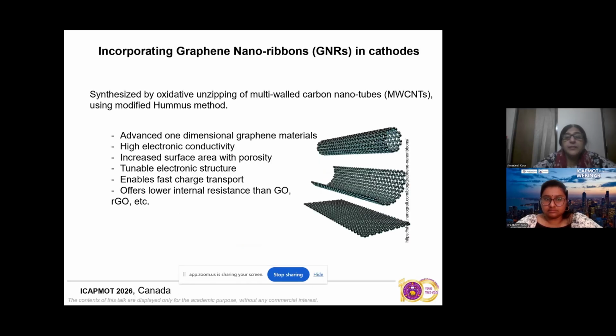So what we have done is we have incorporated the graphene nanoribbons in the cathodes. Why? Because, as I told you, vanadium compounds don't have very good electronic conductivity, but graphene ribbons have very good electrical conductivity, especially at the edges. So we have high electronic conductivity, increased surface area, and a good tunable electronic structure, which enables fast charge transport and offers low internal resistance.